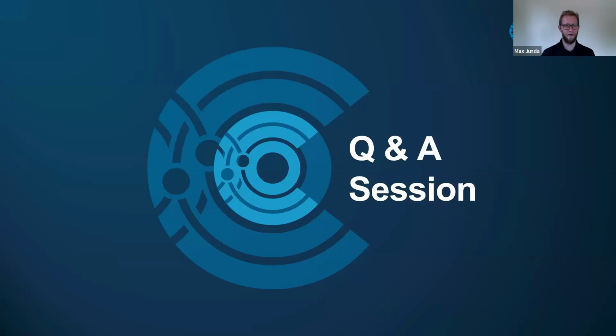Would you like to have a little bit of an interactive answer, Lyle? How about this one? Out of everything that we have, what would we say is the best methodology to measure DLC, which I'm interpreting as diamond-like carbon, thickness of around 2 nanometers? I think we don't know the substrate or the shape or roughness. X-ray reflectivity definitely works in those cases. And I'm assuming ellipsometry probably works too. Yeah, that's my thinking. Ellipsometry could work.